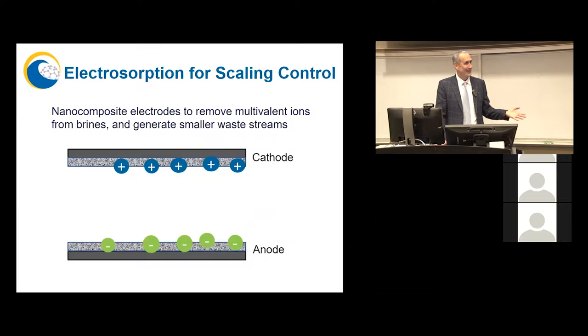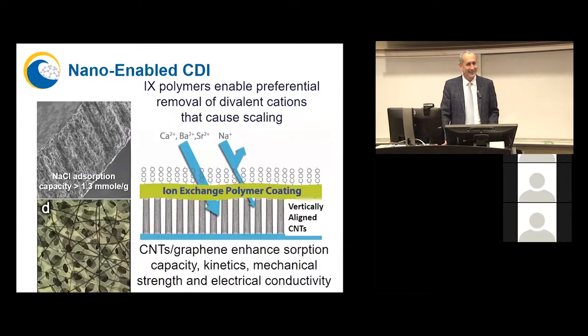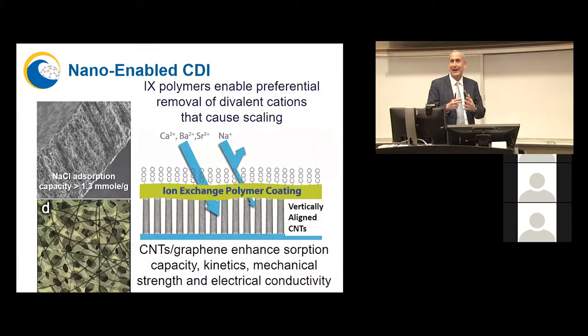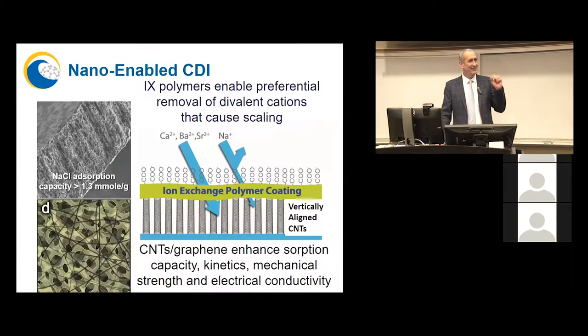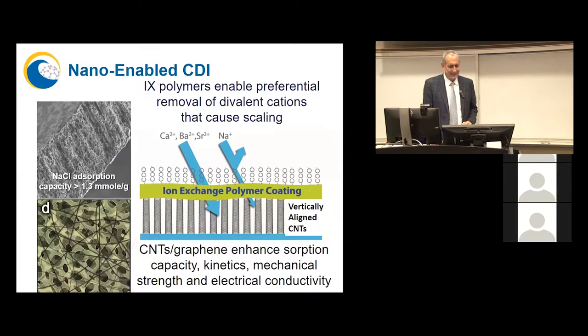So how can nanotechnology help? Well, one logical answer is nanomaterials are primarily all surface. By providing a large surface area, you can enhance the absorption capacity. And I'm illustrating here electrodes that have vertically aligned carbon nanotubes, but it's probably cheaper to use some graphene oxide nanocomposites that also have high conductivity. Now, you can control the pore size distribution so as to minimize the diffusion distance and enhance absorption kinetics, which is also favorable. But more importantly is this.